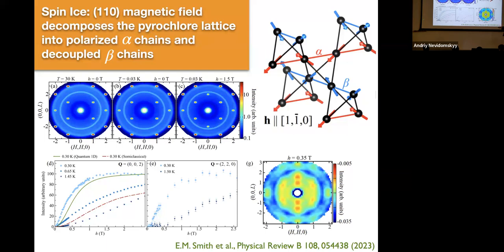So the polarization of the alpha chains leads to new Bragg peaks, which you can see at low temperatures and finite magnetic field, and this is such a Bragg peak here. It's not present at low temperatures and zero field. It's not present at high fields. Now, this is kind of the only new Bragg feature that shows up in this window of view.